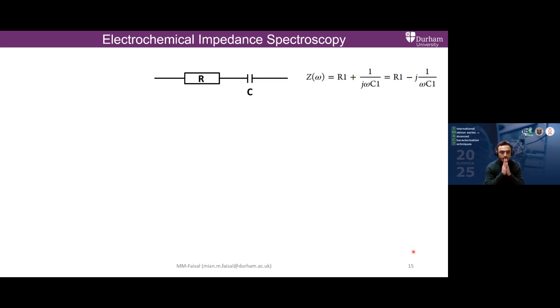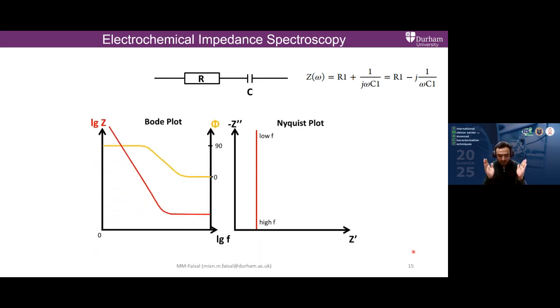What will be the scenario if we connect a resistor and capacitor combined in a cell, and then do an electrochemical impedance measurement? Because there is now a resistor connected with the capacitor, we'll have a displacement of the trend towards the lower frequency region, and then it will again be linear, parallel to the y-axis. That tells you this combination does have a resistance, but since there is a capacitor, we get a linear region in the lower frequency region. Similarly, you can study how the phase changes when sweeping from lower towards higher frequency, and how the impedance changes from higher towards lower as a function of frequency.